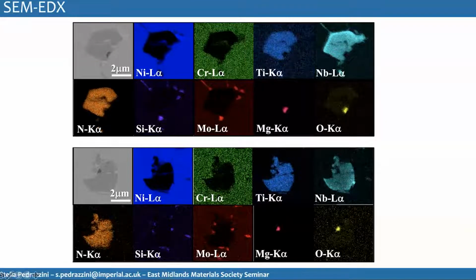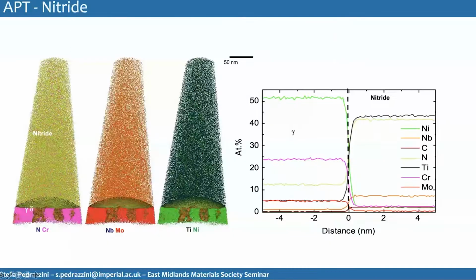And this was not a single occurrence. This was happening throughout the entire sample. So all of the nitrides went from initially being just titanium rich to now being titanium and niobium rich. And that composition was proved by atom probe. So at this stage, with EDX, we have, as I said, an idea of where the elements are going, but atom probe is giving us a quantitative amount. And now we can show that if niobium is this orange one and the nitride is on the right, we can see that this is a titanium nitride that has a lot of niobium now in solid solution, whereas beforehand it didn't.